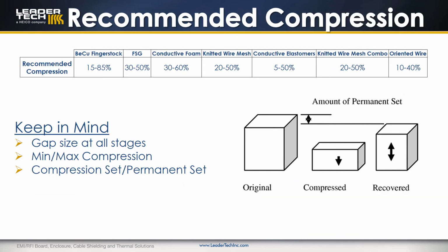All of our enclosure shielding gaskets require compression. We recommend a compression range for each product line and shape. If the gasket is compressed below the recommended range, it may not provide the intended performance. In the case of conductive elastomers, the material is metal particles with a binder. Those metal particles can only contact one another with compression to create electrical contact.